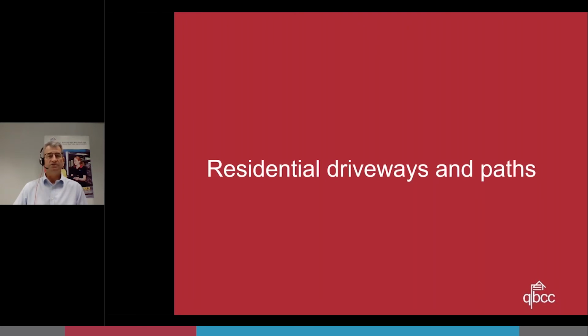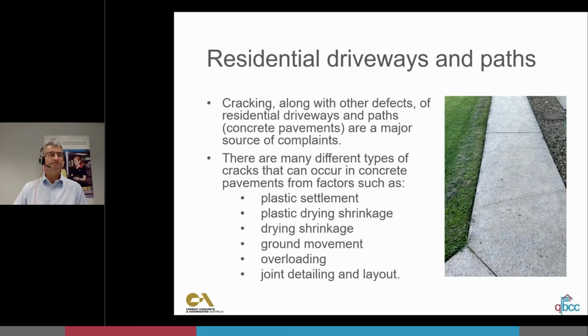So we'll get on to residential driveways and paths. And you can see here there's some nice joints. You've got a saw cut joint here, got another saw cut joint here. But it looks like quite a long distance between these two saw cut joints. So the concrete's shrunk and it's cracked here. So it looks like that's a drying shrinkage crack, and that's probably occurred because the joint spacing's too big.